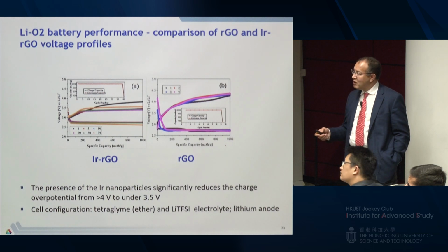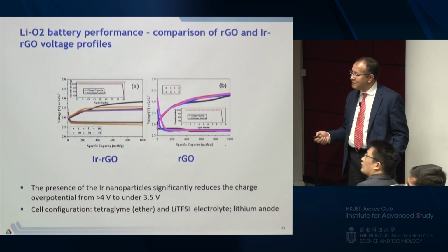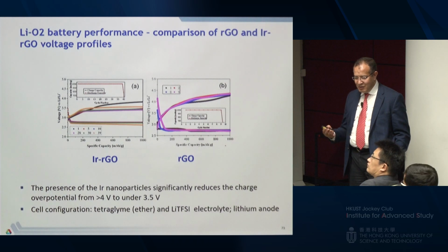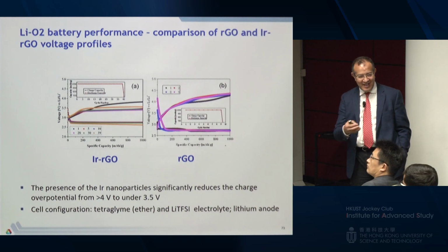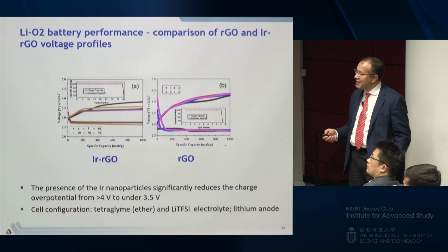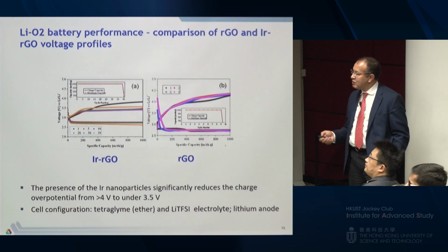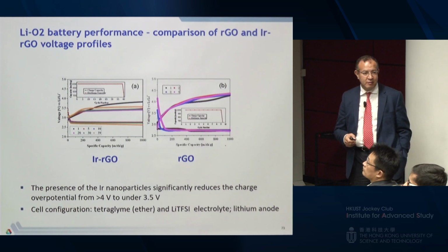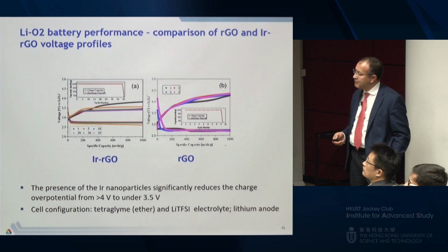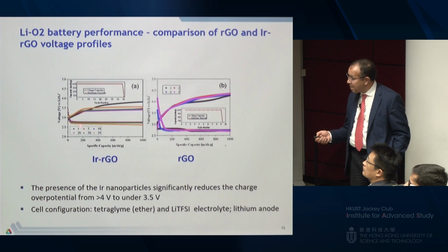membrane. So once we changed the lithium metal, when we opened the cell, we found basically a powder on the anode that's lithium hydroxide. So when we changed it, refreshed the lithium anode, we continued cycling this system for almost 200 cycles. So the first thing we need to do is, what is the morphology of this new system?